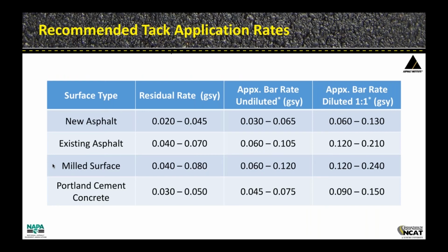What are the application rates? Well, what's really important is the residual rate, whether you're using an undiluted or a dilute emulsion. What we're really interested in is what's left after all the water leaves. This came out of our workshop that we had developed for Federal Highway Administration on tack coat. Depending on the surface that you're applying the tack coat to changes that residual rate. Some surfaces are much thirstier, much more porous, and really can take more or require a higher residual rate than others. If you're paving over a new asphalt surface, you're going to be in that residual rate of 0.02 to 0.045 gallons per square yard. And again, that's residual asphalt.